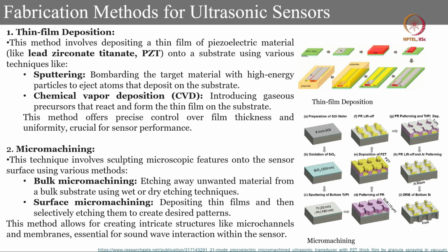There are different ways of fabricating the ultrasound transducer. For example, in the thin film deposition technique, we can use a PZT material. You have a substrate. On this substrate, you deposit platinum, and then you pattern the platinum. Over that, you deposit PZT, and then you pattern PZT. Over that, you can have another platinum layer. You can see that this platinum layer extends like this, and the bottom layer is here. So now you have a piezoelectric material sandwiched between the bottom electrode, which is platinum, and the top electrode, which is also platinum. So, this is your PZT. After this, you can have gold, and on the gold you can have polyimide, and then you can release this whole transducer from your substrate. This becomes a flexible piezoelectric micromachined ultrasound transducer, or just a piezoelectric ultrasound transducer.